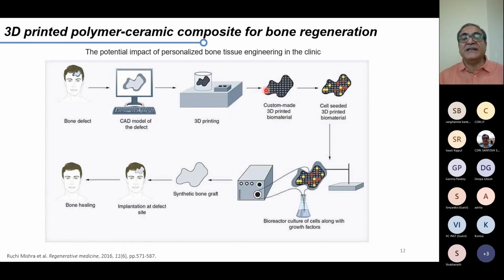So you finally have a honeycomb-type structure here, in any type of shape. You can seed it with cells if needed, but as I said, it is not necessary. If it is seeded with cells, maybe the efficacy becomes higher. You may sometimes have to take the cells from the patient. Bone marrow is easy to take out. Just put the bone marrow directly onto this, grow the cells in the bioreactor and implant it back. This is a general approach.